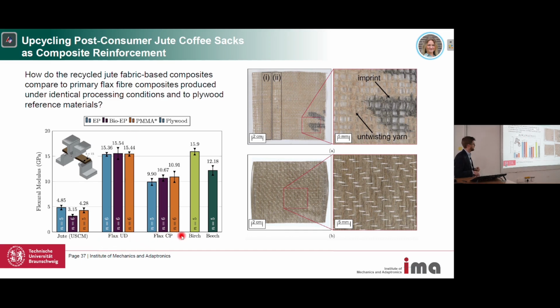unidirectional specimens and flax cross-ply specimens, and also to, at least in Germany, typical birch and beech wood, again under 4-point bending. And we saw that the flax unidirectional material is performing quite well in bending, and it's comparable to wood. The cross-ply, which is 0 and 90 degree plies, which is a fair comparison to the hessian material from the jute coffee sacks, showed that the primary natural fibers are performing much better than the jute, but we had at least some reinforcing effect compared to the neat resin.